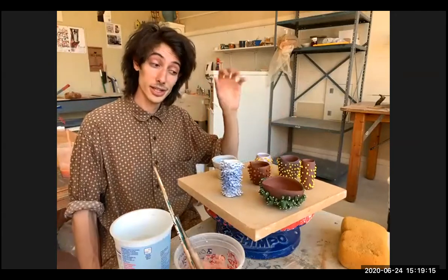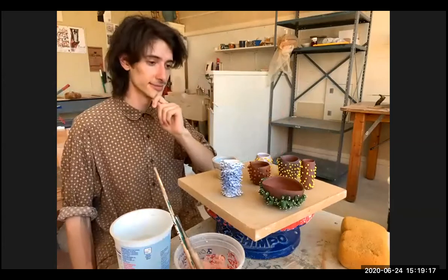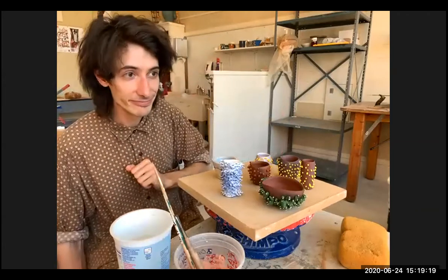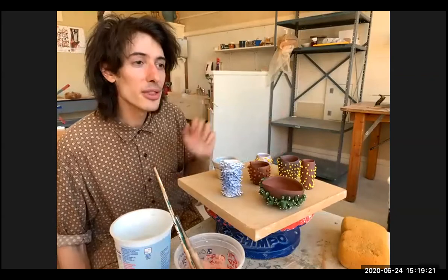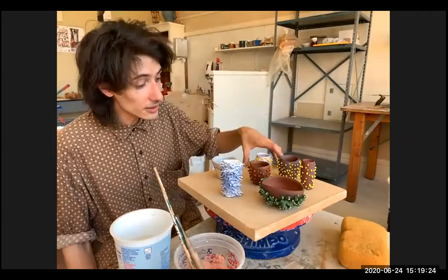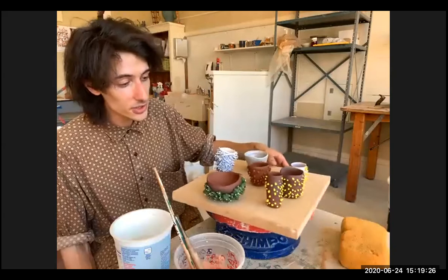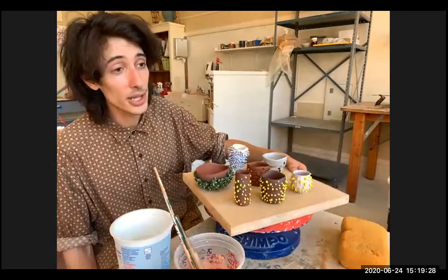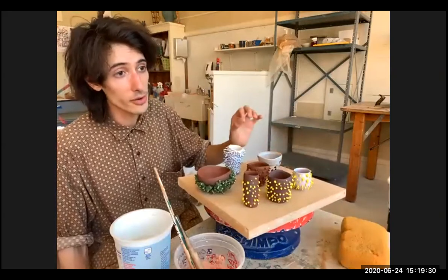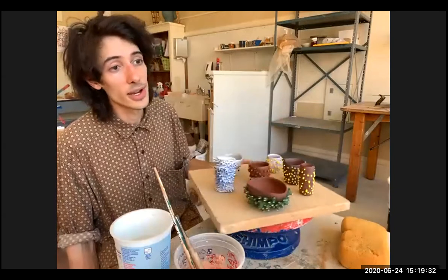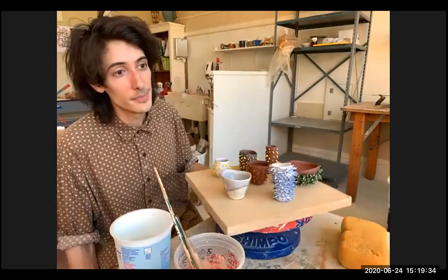These are all fired to cone 6. 5 to 7% is the silicon carbide? One of the frits in this. The silicon carbide, you really don't need much to start the effect. I have some glazes where I use 0.25%, and I have some glazes where I use 18%. So it's really a range.